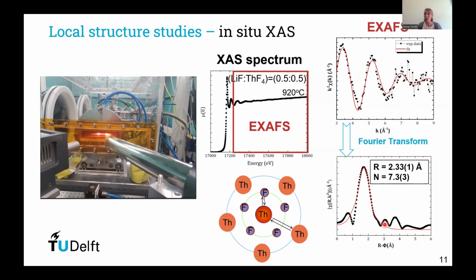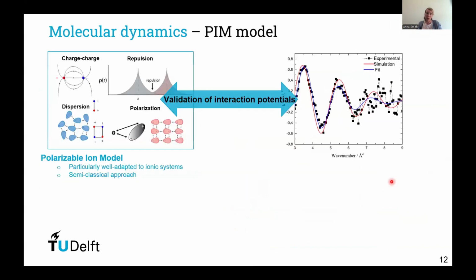We get information on the average distance between thorium and fluorine, in this case 2.3 angstrom, as well as the average coordination number. On average, we found out that there was, at this composition, 7 fluorine ions around each thorium. So that is already some information, but not a very detailed information. If we want more detailed information, we need to couple this experimental approach with molecular dynamic simulations.